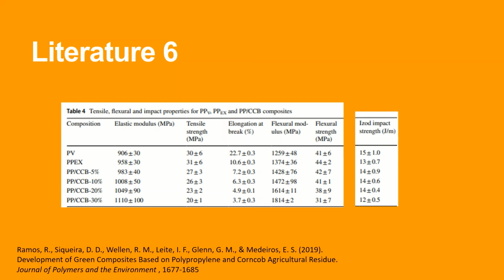Moreover, the obtained tensile strengths were lower in comparison with the neat processed polypropylene and unprocessed polypropylene, with values 30 plus or minus 6 and 31 plus or minus 6 megapascals, respectively. The elongation at break of the composites was also observed to decrease with addition of corncob. At 5 weight% filler content, the elongation at break value was found to be 7.2%, which decreased to 6.3% at 10 weight% filler content, and so on, still lower than the neat polypropylene.